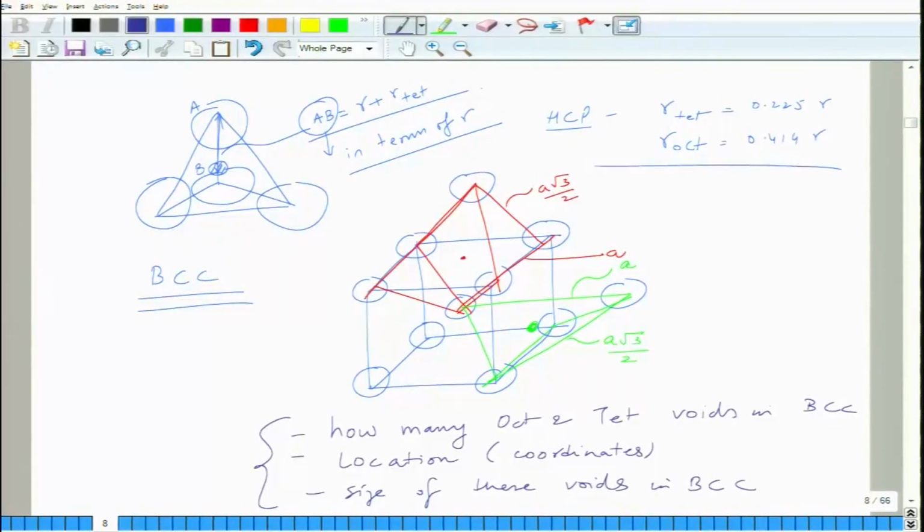These are the octahedral and tetrahedral voids which are present in metallic structures. These voids are useful because the impurities go in them, because nothing is pure in nature. Steel contains carbon, and carbon is a smaller atom, it goes to interstices, and that makes the steel stronger than pure iron. These interstices are also important when we consider ionic solids, because in ionic solids anions are bigger, cations are smaller, and cations occupy the interstitial sites. That is where the knowledge of these interstices is very useful.